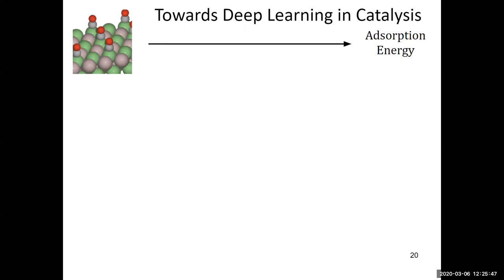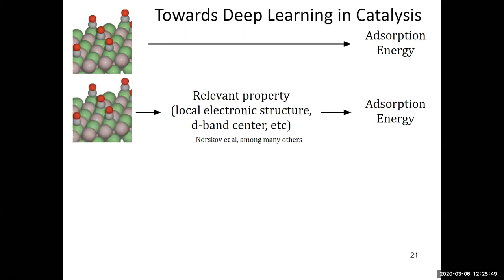Standard structure property relationship. And the thing that really drove the field forward 20 years ago was realizing that there's a reason why different materials bind adsorbates differently. And in a lot of cases, you can think about what is the electronic structure of the surface, like the d-band center, and how is that going to change how you bind things. If you modulate the d-band center, you change the binding energy. And so the idea was you look at a surface, you calculate the d-band center, and then basically off of that d-band center, you make your prediction for what the adsorption energy is.